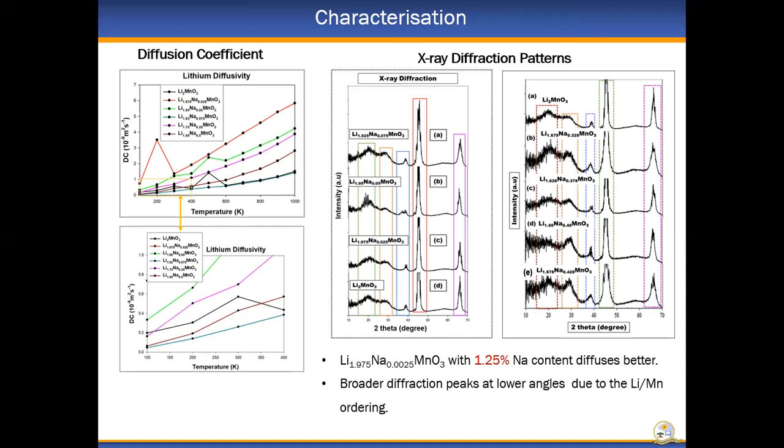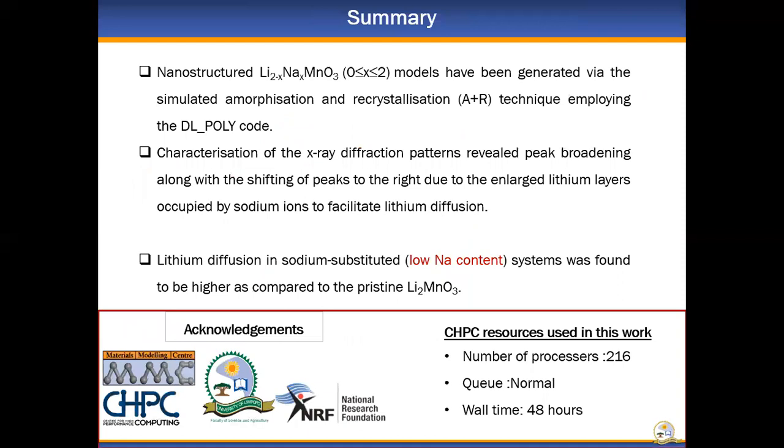which enlarges the lattice. In summary, sodium substituted systems were generated using the amorphization and recrystallization techniques. Characterization of our results shows that sodium can actually increase the lithium diffusion because sodium has a larger radius than lithium. Our results also reveal that structures which contain less sodium were stable as compared to the ones containing large amounts of sodium.